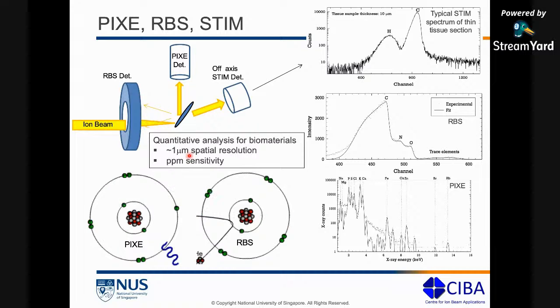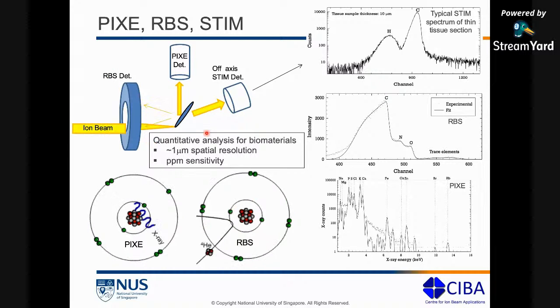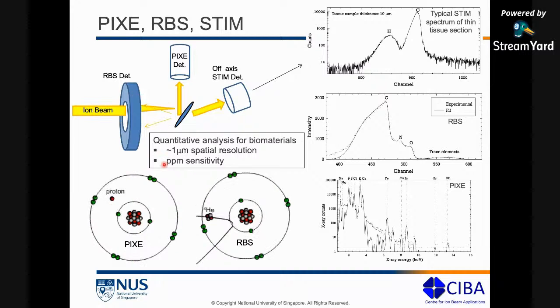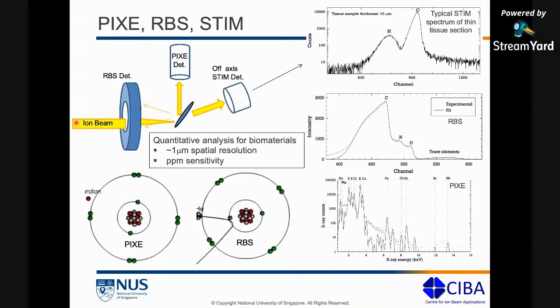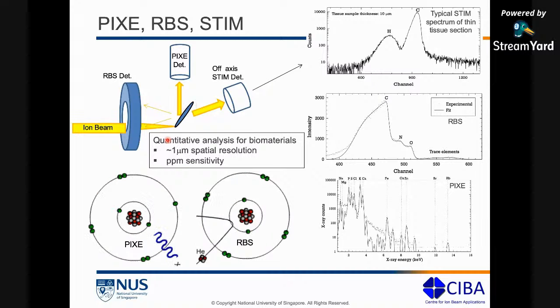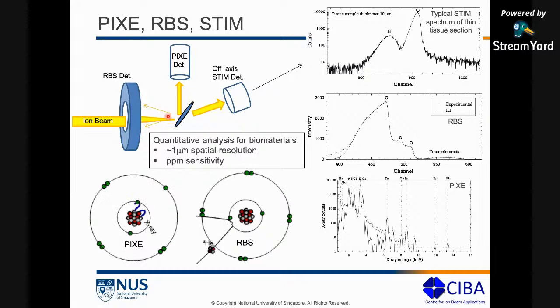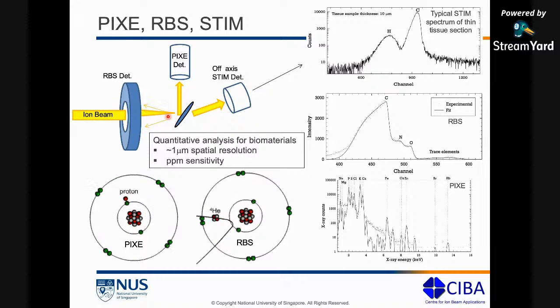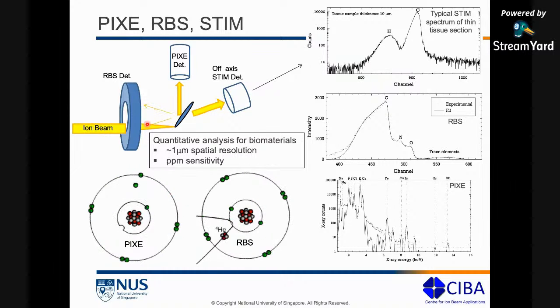And then on any given experimental day, this is the typical setup that we will have in our chamber, right? So we have an incoming ion beam. So at this point, it's just a broad beam. We have a sample in the center. This is a fairly thin cellular sample. The beam is focused down to a small beam spot, typically on the order of 1 micron. We then scan the beam along the surface of the sample.